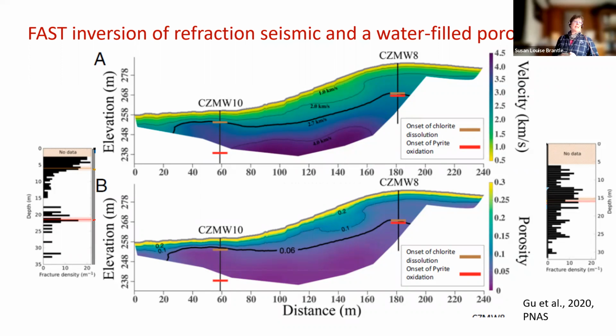Now, why do we think the P wave velocities are telling us about the porosity and not the fractures? Well, first of all, I think you could probably make a fracture model that explained this just as well. So it's non-unique to say that the seismic transect is explained in this way by the porosity. You could make a fracture model, but what we see is that the fracture density, this is from the televiewers in the borehole down here, and this is the fracture density in the borehole up here. The fracture densities don't seem to correlate with what we see from the seismic, whereas the porosities do.